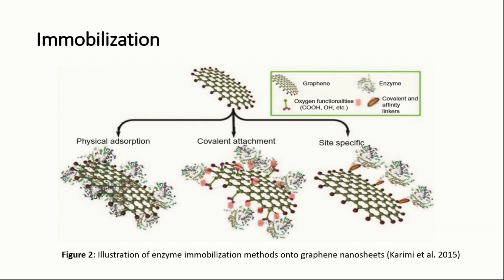Immobilization is the confinement of biomolecules in a substrate which preserves the biomolecules' activity and stability in the environment. It can be done through reversible methods or irreversible methods. Reversible methods such as different physical adsorptions like pi-pi stacking, hydrogen bonding, and electrostatic interaction are weak and non-destructive, but irreversible immobilizations such as direct chemical interactions through functional groups and cross-linkers are much stronger and are destructive.